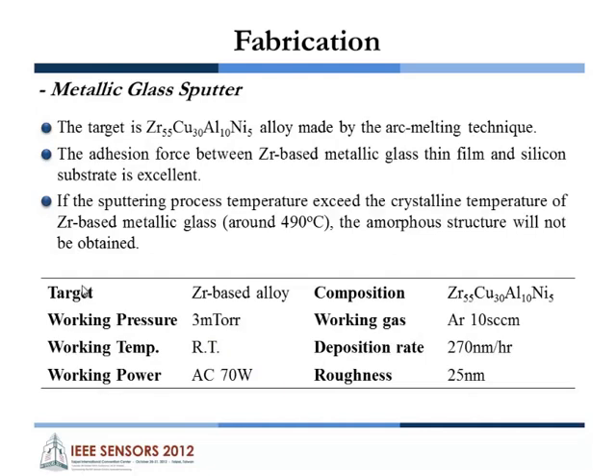We deposit the metallic glass by a sputter machine, and the sputter conditions are shown here. The target is a zirconium-based alloy, and this zirconium-based alloy is made by the arc melting technique. By the arc melting technique, we can get a more uniform distribution of all elements. During the sputter process, high temperature should be avoided, because if the sputter process temperature exceeds the crystalline temperature of the zirconium-based metallic glass, the amorphous structure will not be obtained.